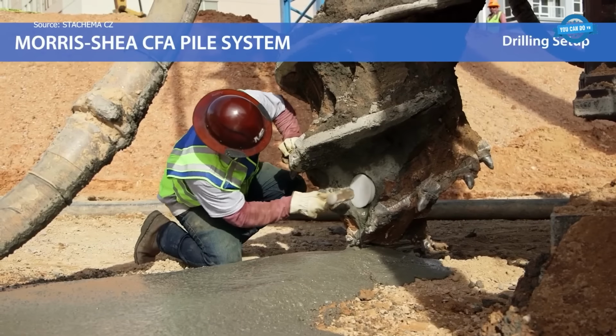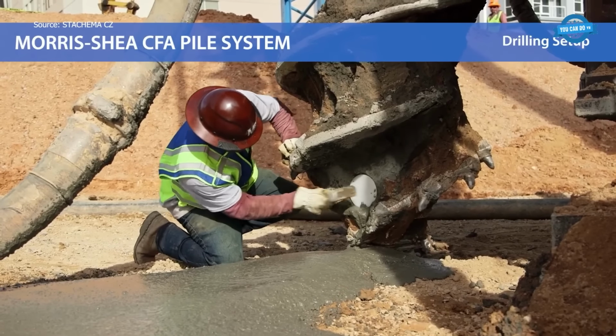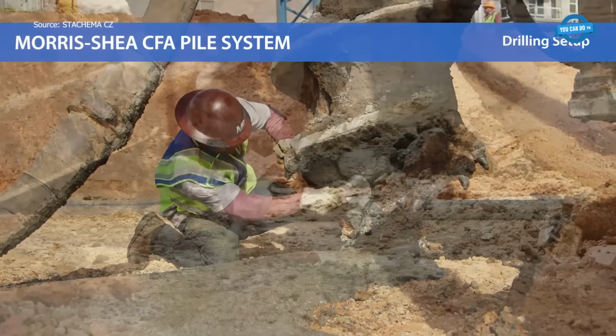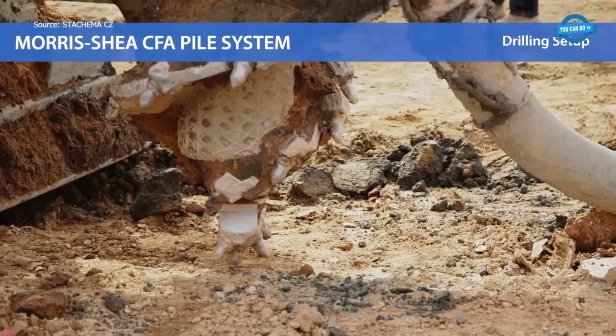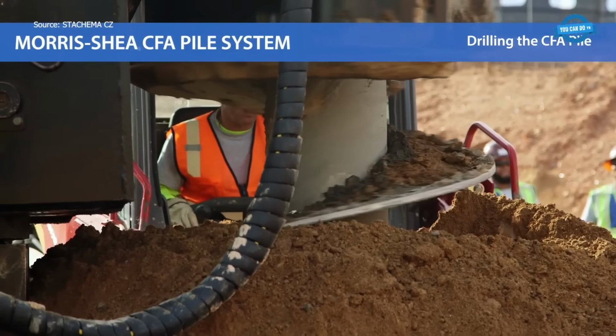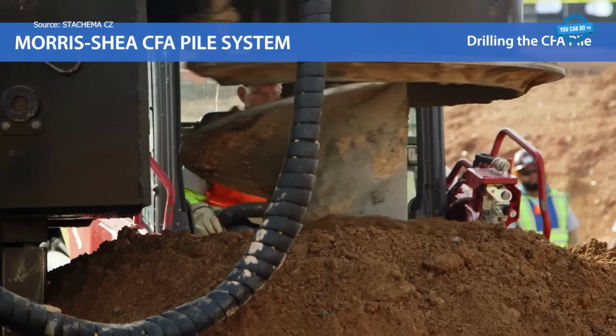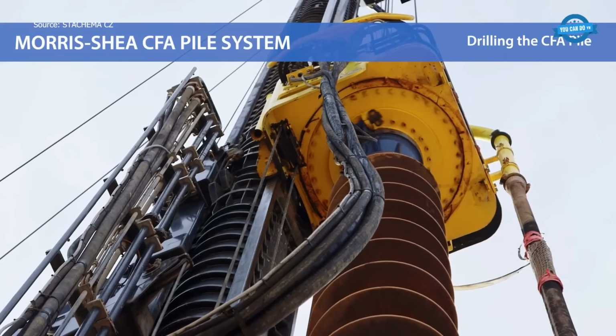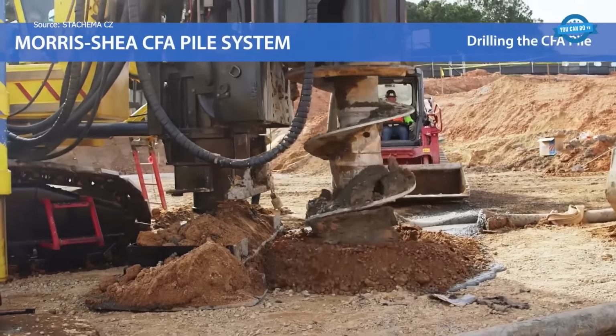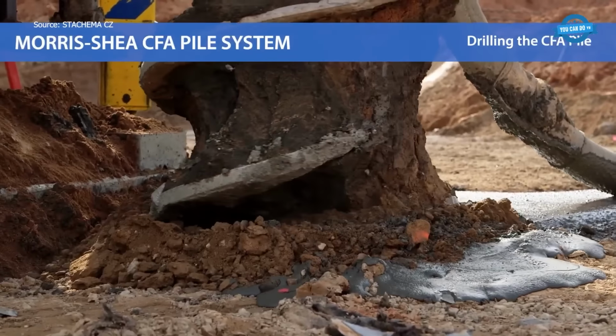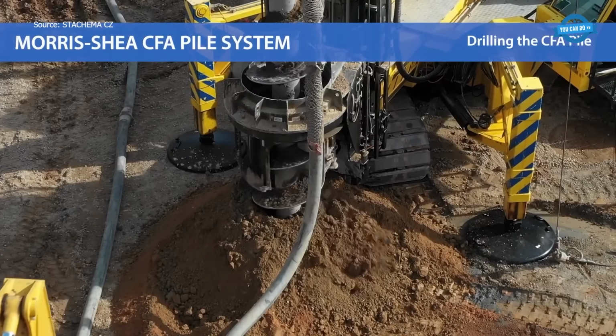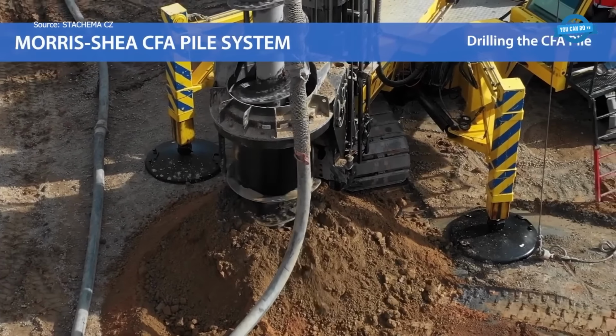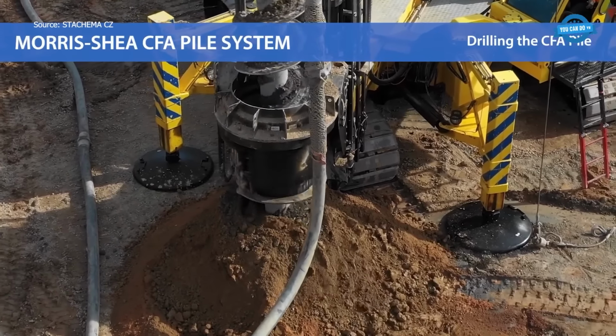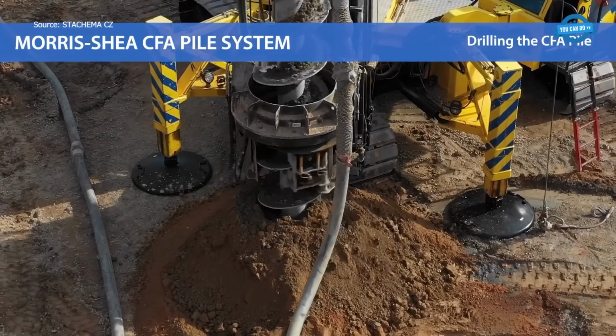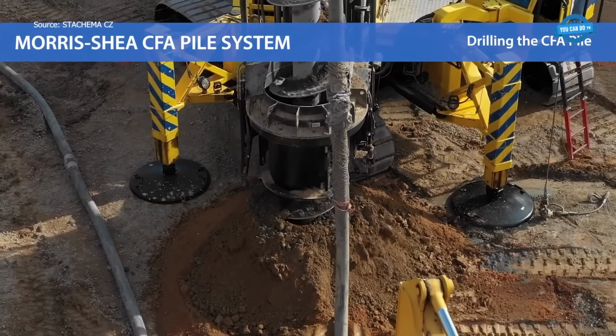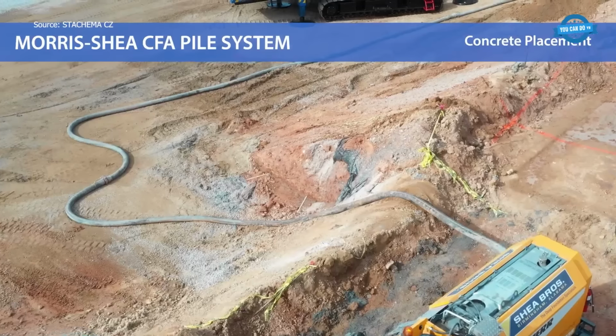Morris-Shea CFA continuous flight auger pile can be installed without a single steel casing on site. This system advances a continuous flight auger into the ground to the required depth without temporary or permanent casing. As the auger penetrates, soil is conveyed upward along the flights and removed at the surface. Continuous monitoring of depth and torque confirms the pile reaches design capacity. Once target depth is achieved, concrete is pumped through the hollow stem while the auger is steadily withdrawn. That upward movement replaces excavated soil with concrete in one controlled sequence. Seriously, no second chances here.